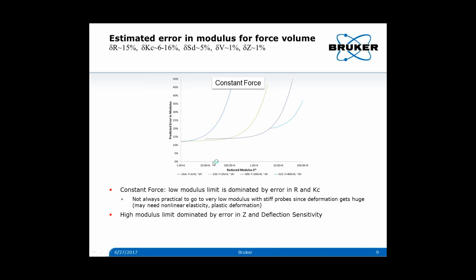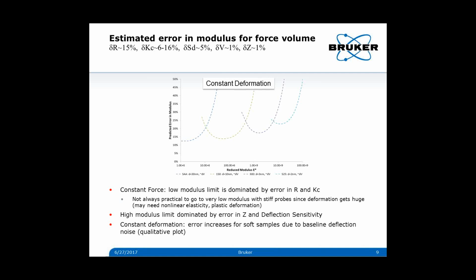So you can see that for low modulus samples, the error is dominated by error in tip radius and spring constant. And now it's not always practical to go to very low modulus with a stiff probe because you get these huge deformations and you're going to lose resolution. You may also get out of the linear elastic regime. At high modulus, you're limited by error in Z and deflection sensitivity. If you instead try to keep the deformation constant, then it comes up at lower modulus, but really the minimum is kind of determined by the same thing, the error in the radius and the spring constant. And then finally, in peak force tapping, the Z error is higher than it is in force volume. That'll add around 5% to the force volume error, assuming everything is done well.